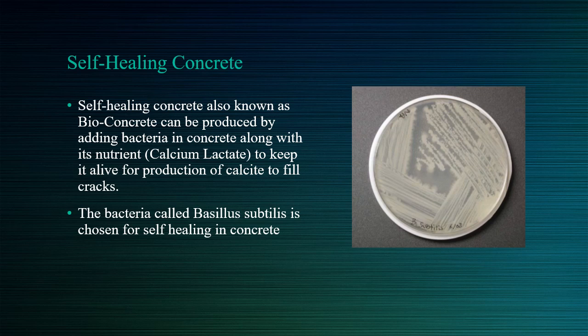The bacteria used is Bacillus subtilis. Why Bacillus subtilis? Because it is able to adjust to the alkaline atmosphere in the concrete for the production of calcite. It also produces copious amounts of calcite without being affected by the calcium ion concentration.